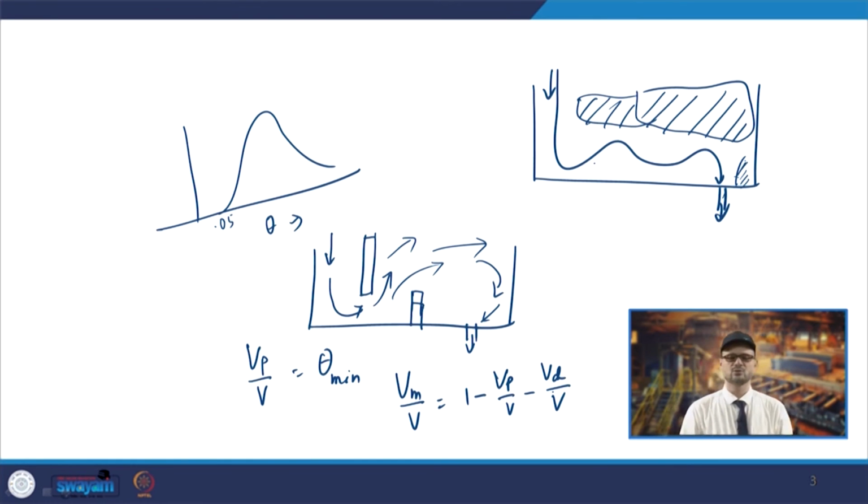So, that way you calculate. You will have the mean residence time coming in actual, and based on that, for the 2 theta values you can calculate the residence time, and then you can have the fraction of the dead volume. So, that will be the dead region and the plug region. Accordingly, you can have the calculation of the well mixed zone in that case. So, that way the different components, the plug region, the well mixed region, as well as the dead region, are found out.